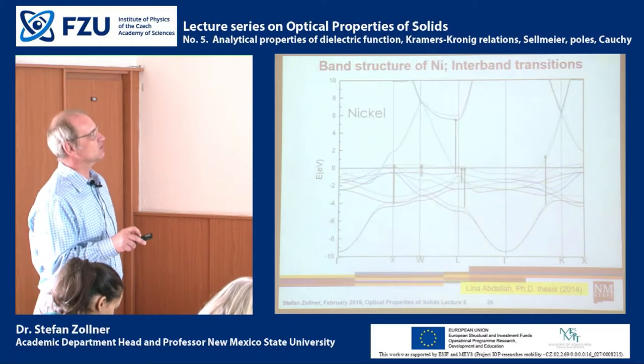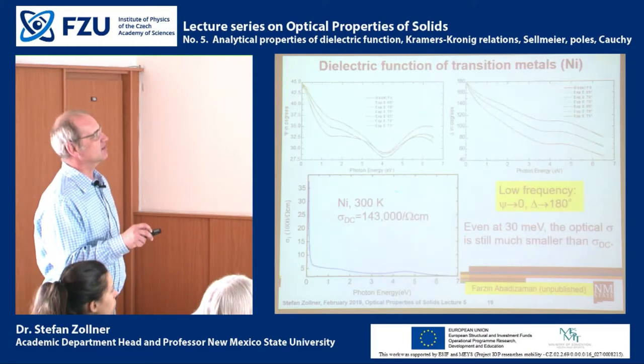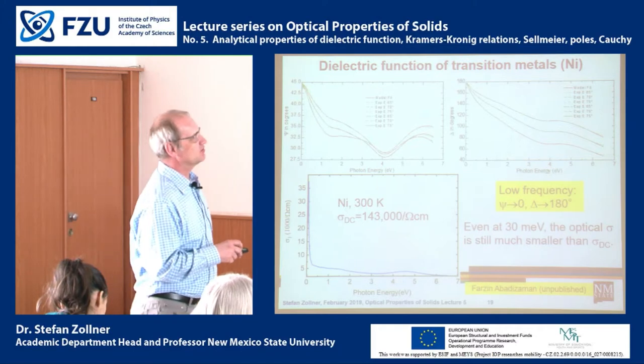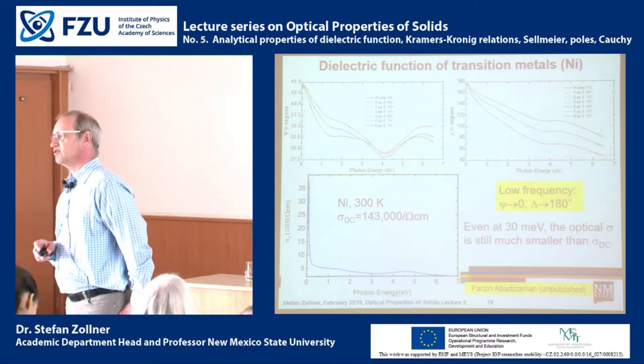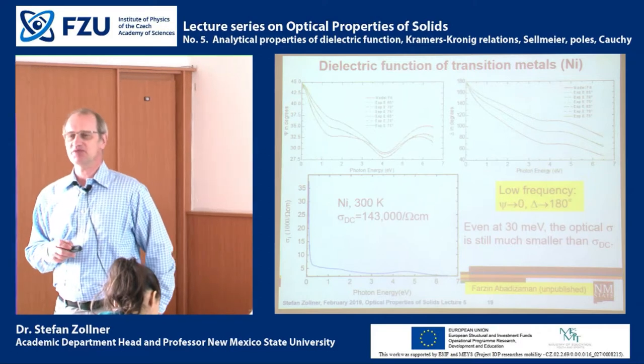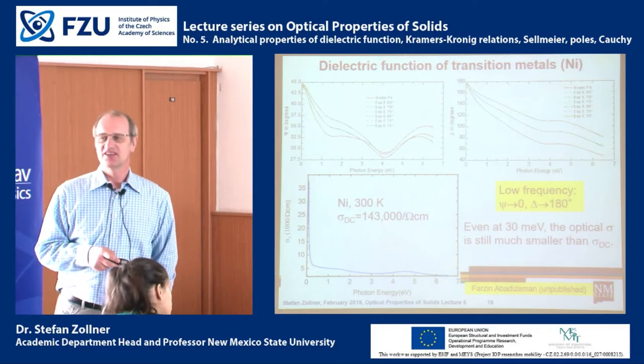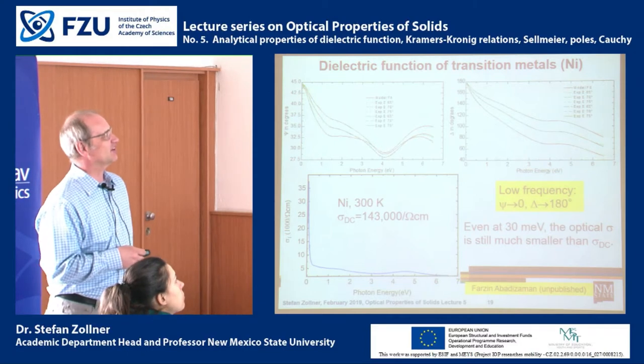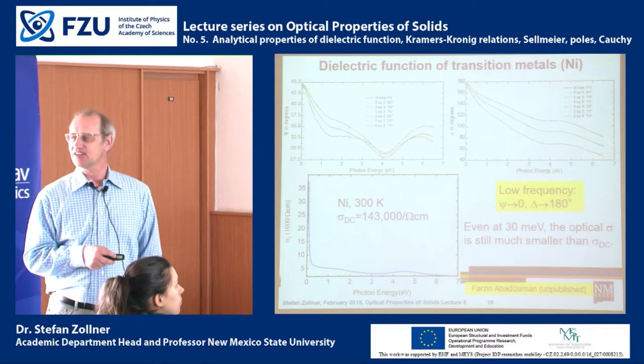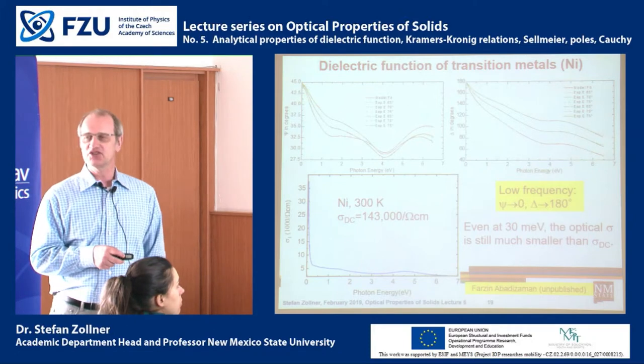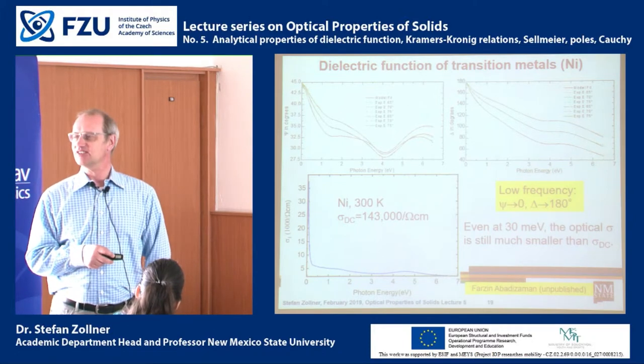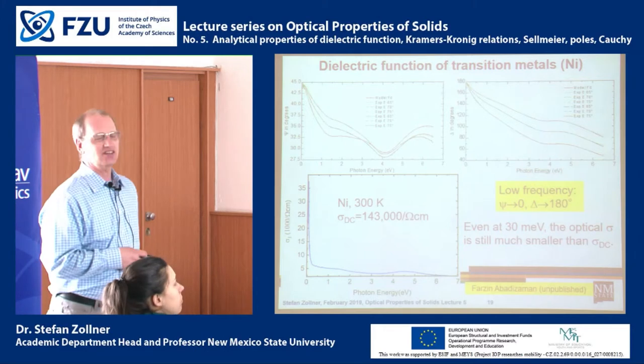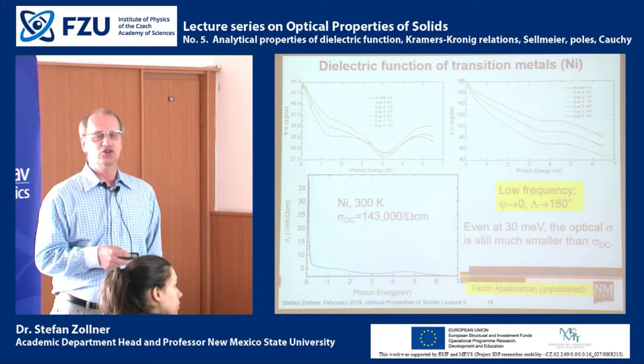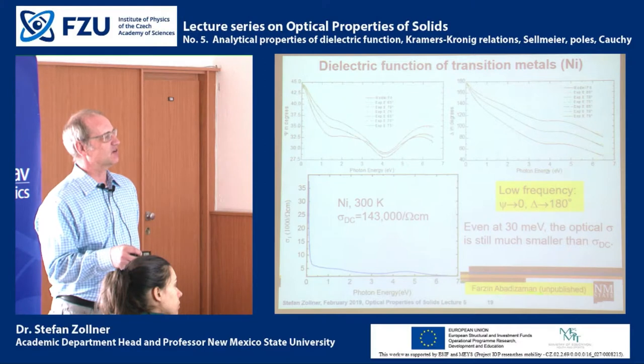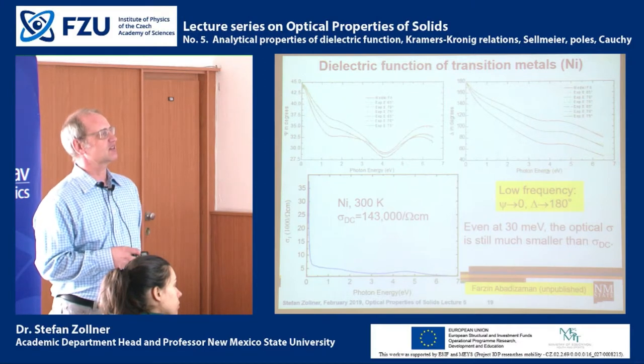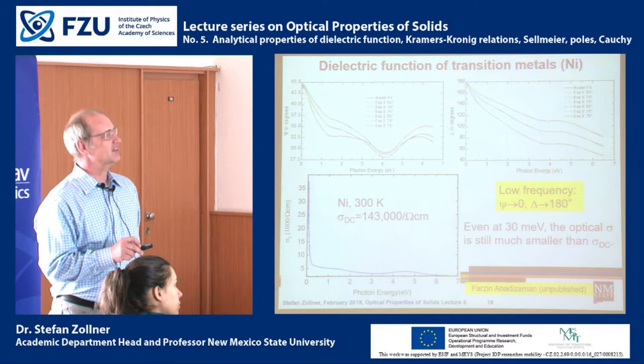And in order to get these data here, we've spent 5 years trying to clean the nickel surface. So how do we prepare the best nickel surface? We've been working on that for 5 years. I think we figured it out now: we have to put the nickel in UHV and heat it at 500 degrees Celsius overnight. That has been the most convenient way for us, and that was Farzin's work. That's what we found to be most effective in order to clean the surface.